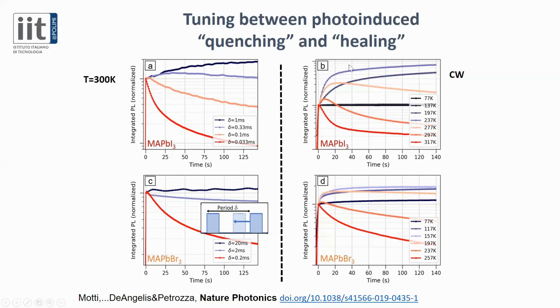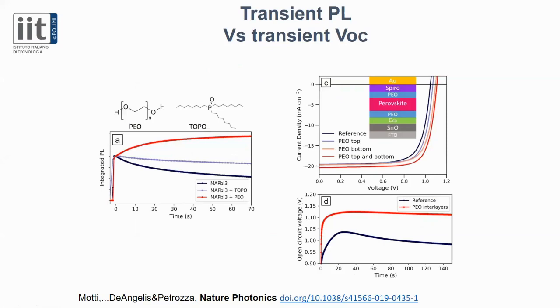And the same thing happens when you change the temperature of your system, which means that you are providing extra energy to the semiconductor. What is interesting is that if we stay at room temperature in CW condition, which is the working condition of a solar cell, we can switch off the photo quenching phenomenon, which happens in the pristine perovskite thin film, the dark line on the left, leaving only a photo healing phenomenon when we use a proper passivation of the surface.